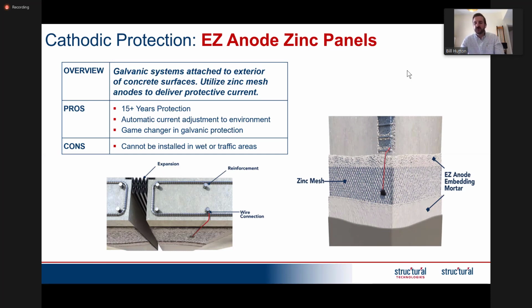Somewhere we install a lot is for expansion joints. So for example, if you have a retaining wall in a basement with expansion joints, typically if those expansion joints have been leaking, between 3 to 5 meters either side of the expansion joint, there will be a high risk of corrosion. So they're the areas which require protection. And this kind of reiterates what was talked about yesterday by Morty, and that is, really providing optimized solutions. So if your basement wall is not 100% at risk of corrosion and you only have a risk near the expansion joints, then you only need to invest money in protecting near to the expansion joints. And that's where this system can provide good benefits.